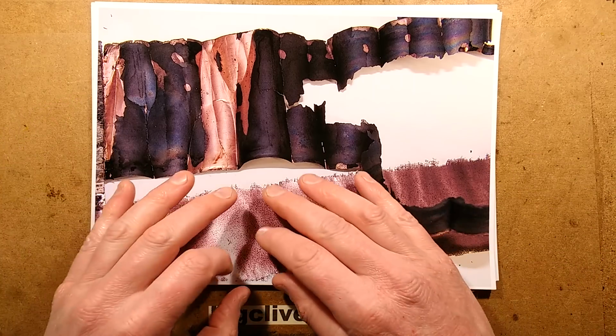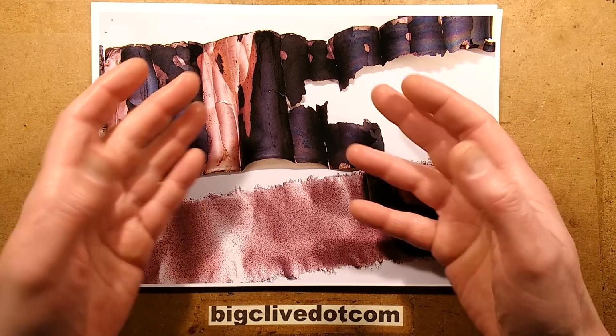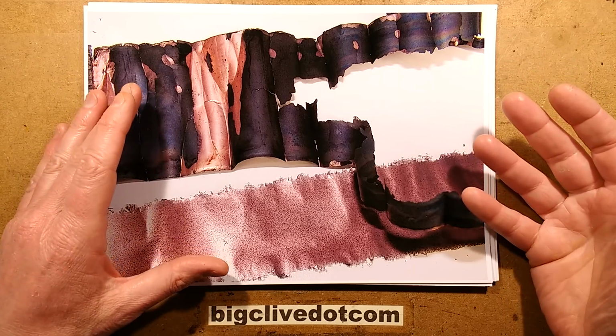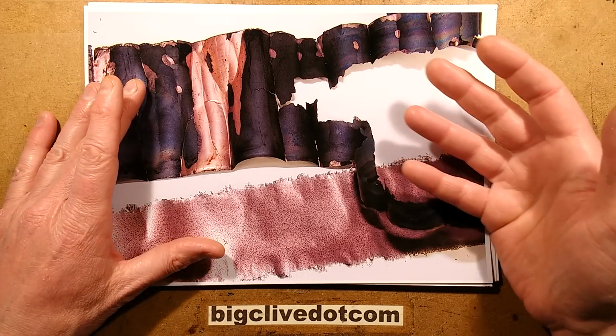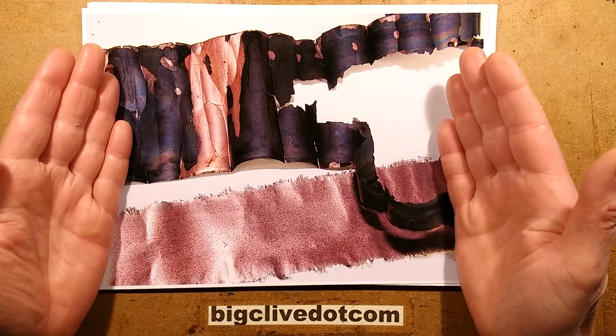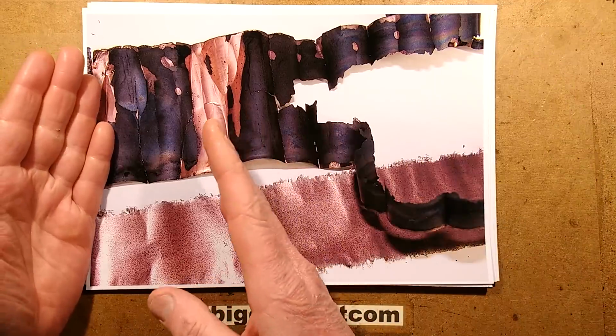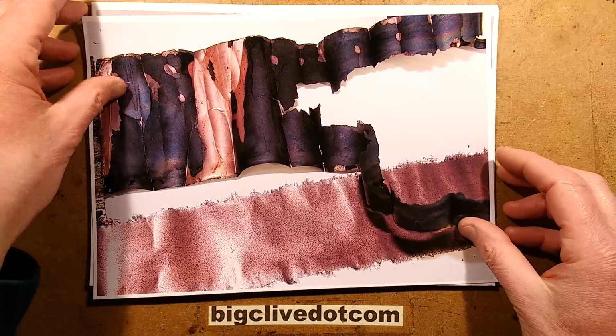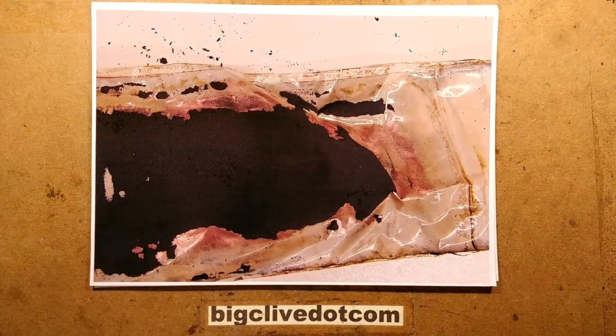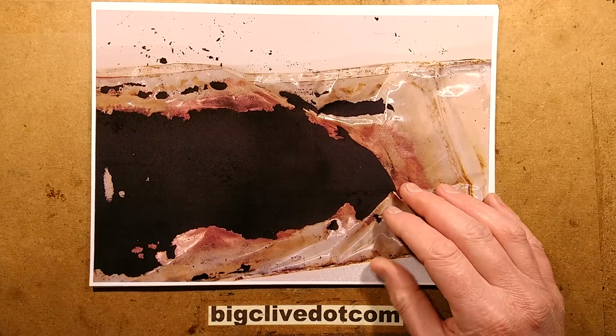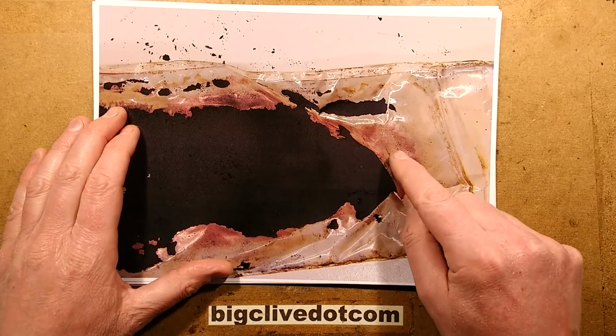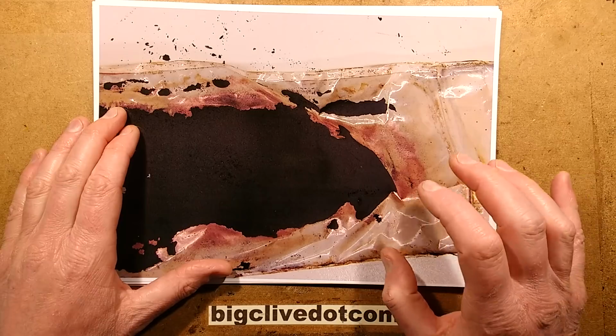The copper was very eroded and it had pitted quite heavily, and it had carried through. It had tried going basically from the copper side to the aluminium electrode side. And in doing so, the separator in the middle got absolutely copper plated, but it's much more interesting this.